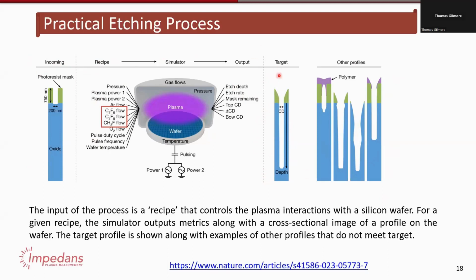So again, just keep in mind that if you want to etch something down here, the ion cannot be at an angle more than arctan of CD over depth. Okay, so that could mean that for like a 200 to 1 aspect ratio, any ions greater than 0.3 degrees with respect to the normal of the surface are going to collide with the walls before they hit the bottom, and there will be ion angular spread. And in fact, I'll show you some data a little later, but when you're looking at a situation like this, you actually have an etch rate as a function of depth due to the ion angular spread. So that's something we need to measure.